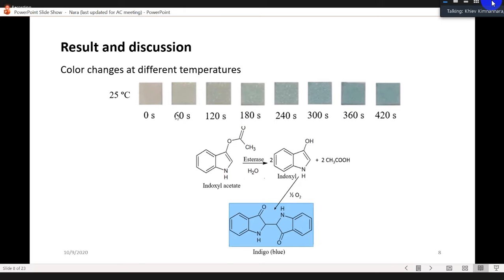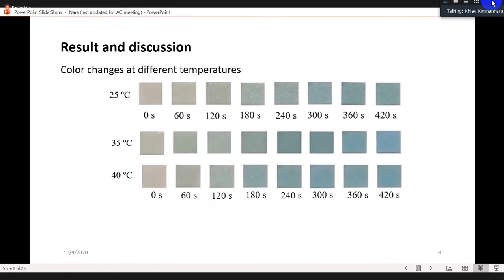So I also observed higher temperatures, and I got the result like this. At 35 and 40 degrees Celsius, we can see that the color change to greenish blue seems to be faster than at room temperature. But it might be somehow difficult to judge the color changes between 35 and 40 degrees Celsius.